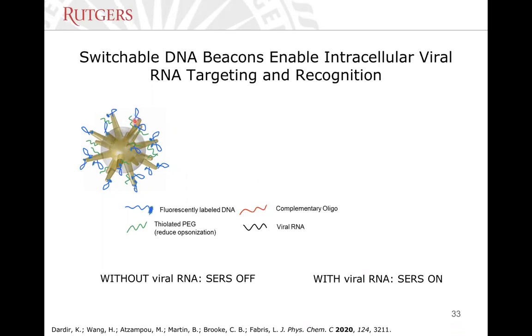fluorescently labeled at the 3', thiolated at the 5', and also designed to have self-complementary flank regions at the termini, so that when the oligonucleotide is left alone, it folds into a beacon loop. In this position, the fluorophore is near the metallic surface. And because every time a fluorophore is near a plasmonic metal surface, it gives SERS signal, whereas the fluorescence is quenched. So in this case, this nanoparticle produces a highly intense SERS signal.